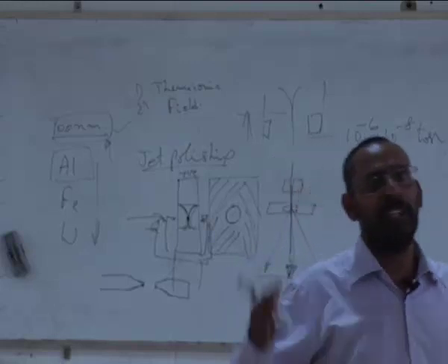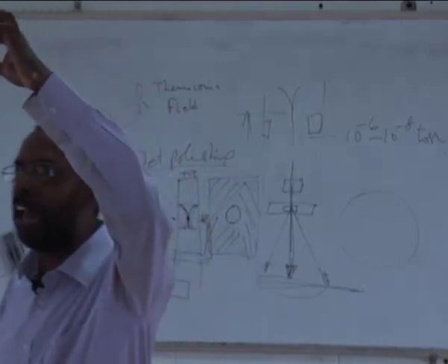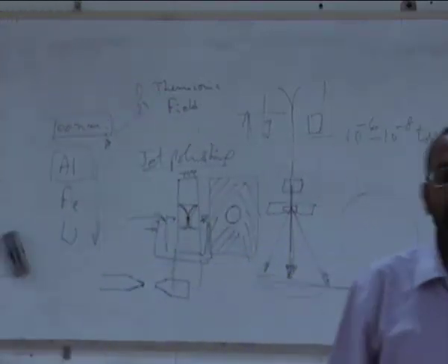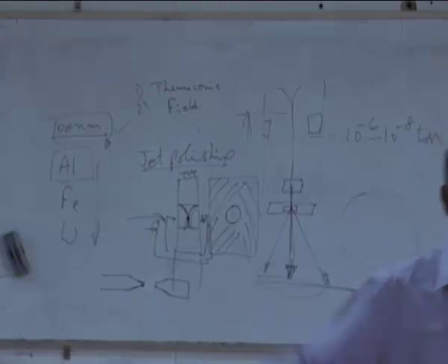Electropolishing is based on a principle that your sample can be made into an anode, and your container with electrolyte can be made into a cathode, and the circuit has to be completed. When will the circuit get completed? Only when your sample is conducting.